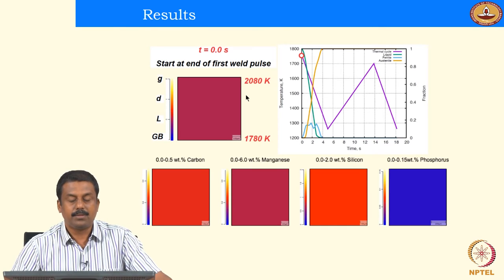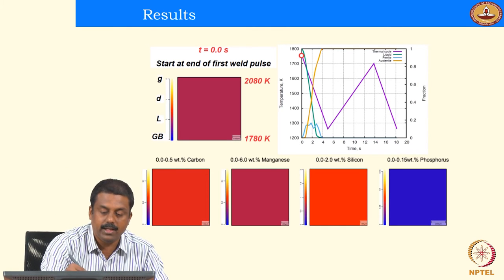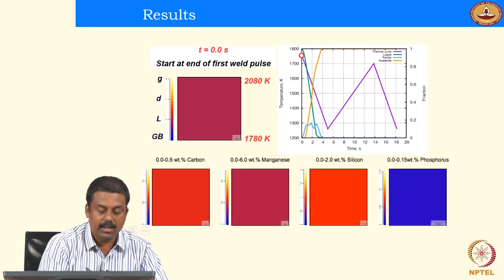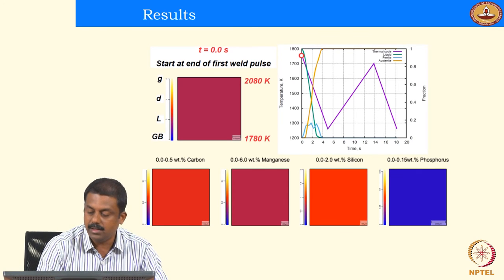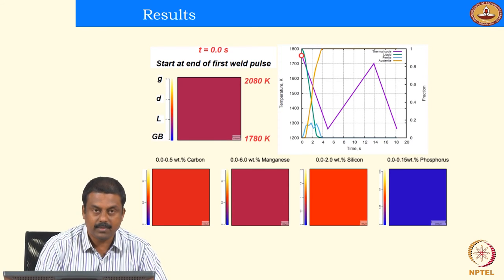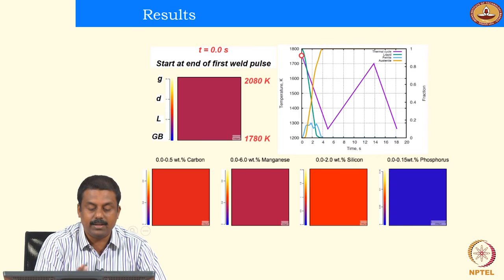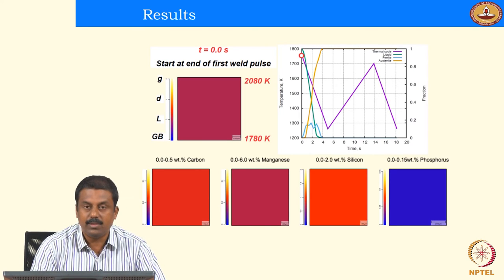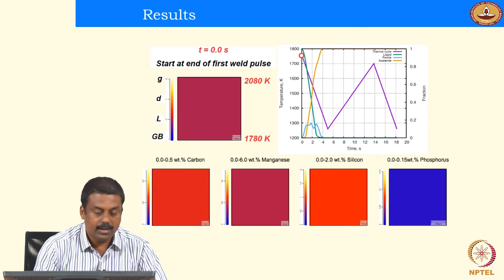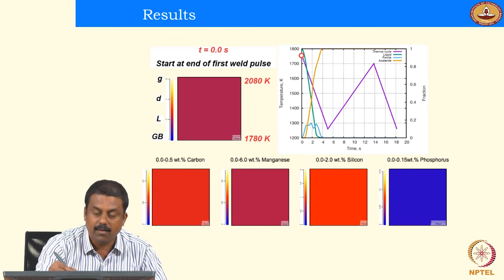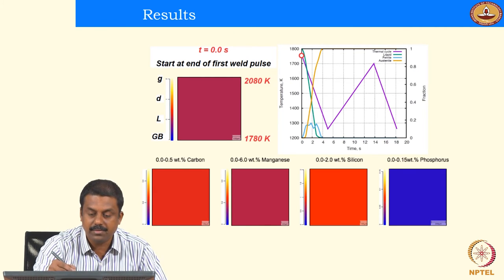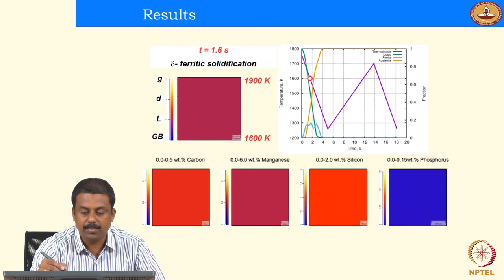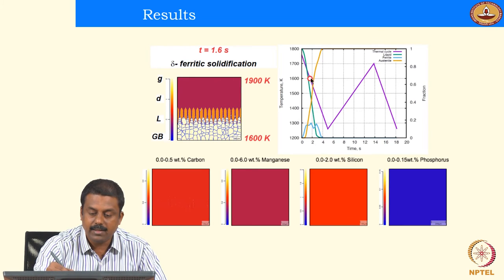Okay, so at time T0, everything is liquid, right? It's weld center. So everything is liquid over here, and you will have a uniform distribution of carbon, manganese, silicon, phosphorus in the liquid. It is a single phase liquid, right? So when it is liquid, all the elements are homogeneously distributed. And then when you start cooling down after the current is passed, if you switch off the current, the pulsing is completed. When it cools down, say for example, when you reach a temperature of 1600 Kelvin